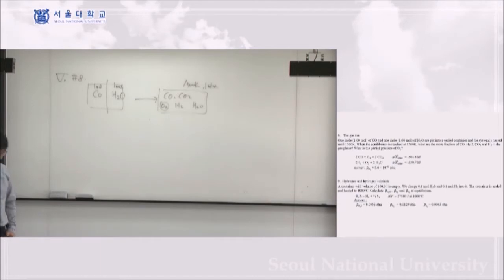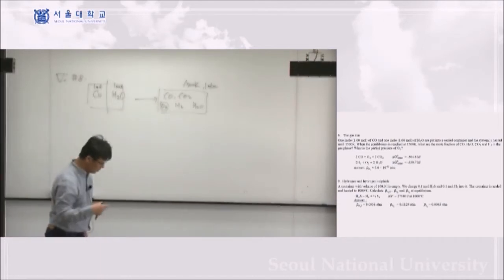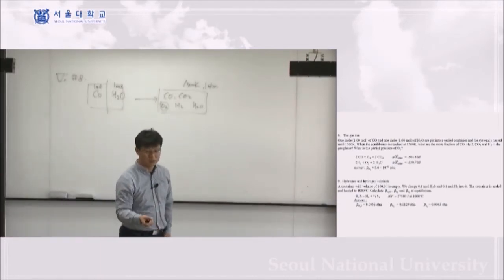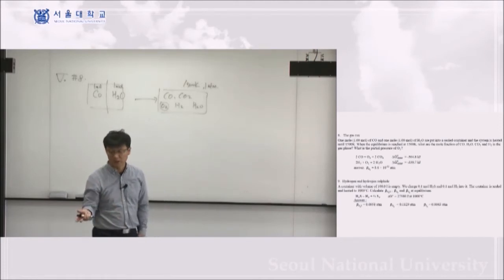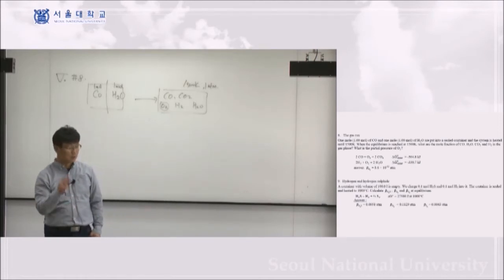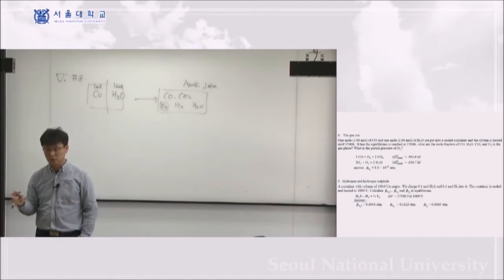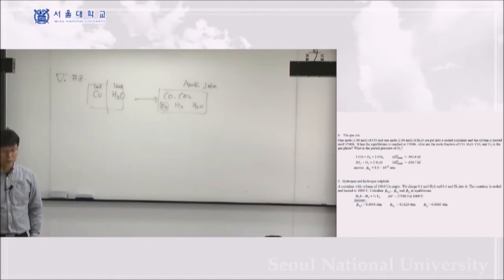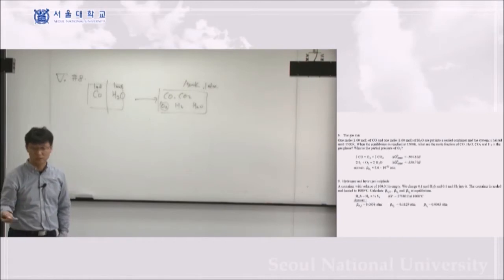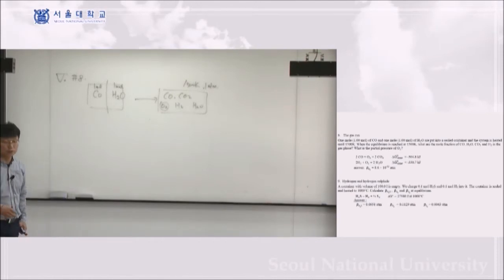And then when you are asked what the final state is, it means we are assuming that this is the equilibrium state. So in the final state, for all the chemical reactions you can set up inside the system, whatever the combination is, delta G should be 0. Delta G of reaction should be 0. That's the final equilibrium state, chemical equilibrium state, okay?